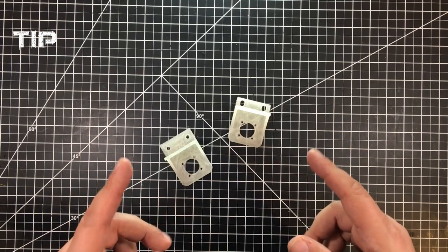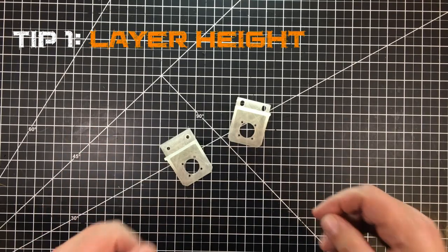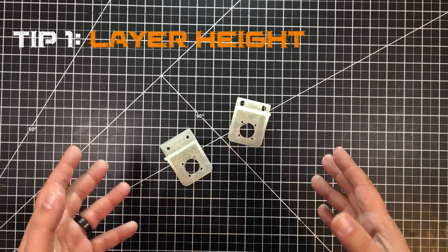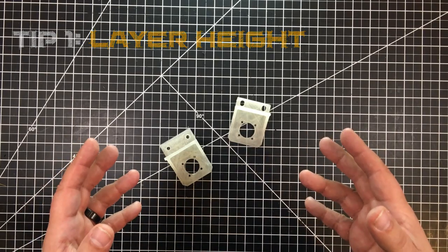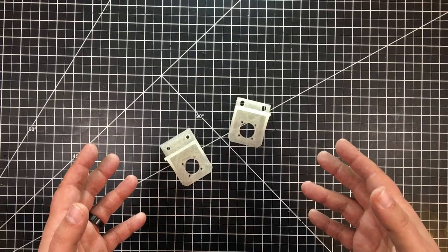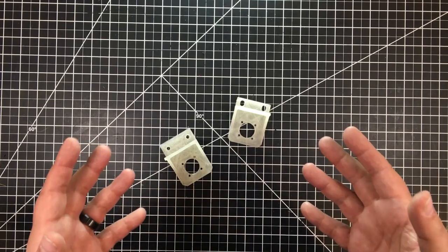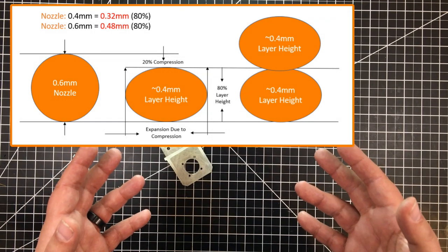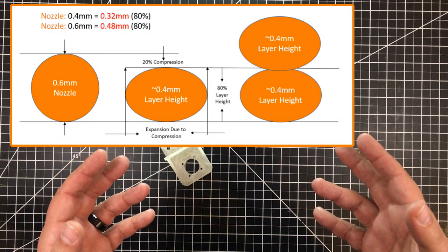The first tip I'm going to share with you is layer height. You want as few layers as possible. The more layers you have, the more potential there is for delamination. So what I use is the max of the 80% rule. So whatever 80% is of my nozzle diameter, that's what I will use for my layer height.